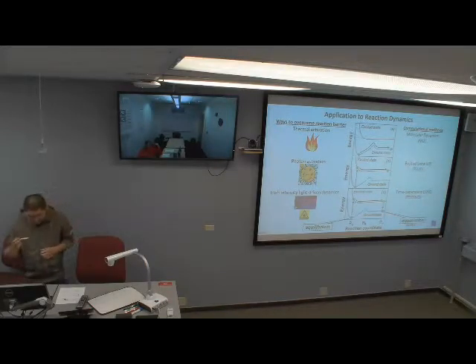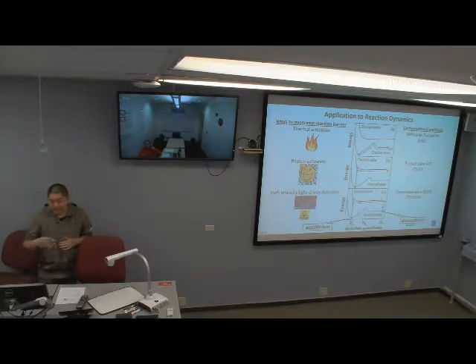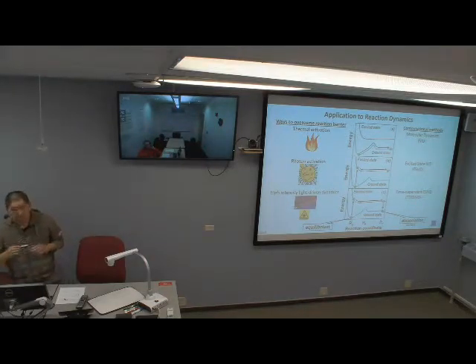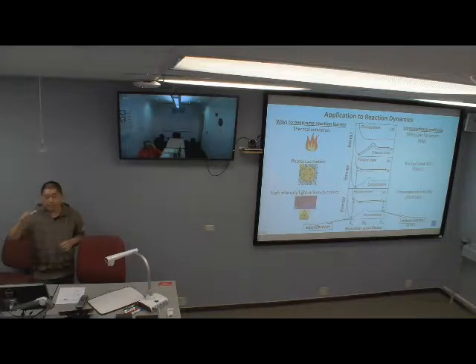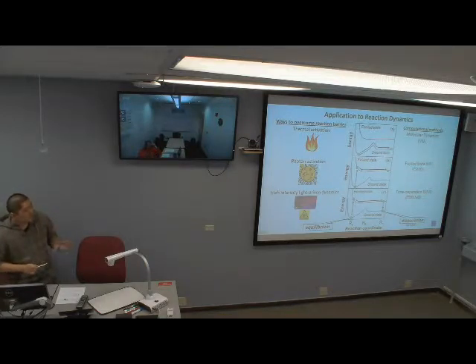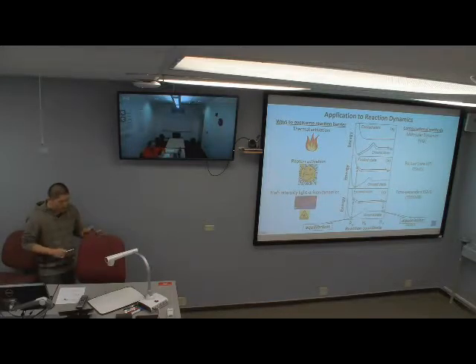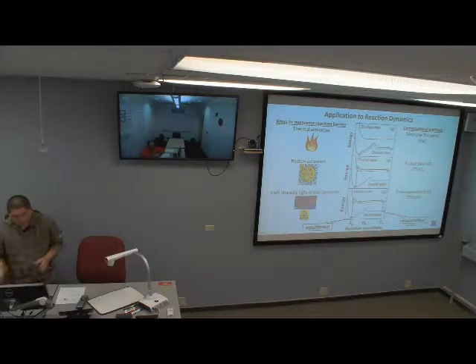And in TDSMD calculations, electrons are hopping between ground state and excited state. So first, the electrons are promoted from ground state to excited state, and then electrons are relaxing from excited state back to ground state. So this is called a Rabi cycle. TDSMD calculations consist of many Rabi cycles. During these Rabi cycles, the system accumulates kinetic energy and finally overcomes the dissociation barrier, leading to photodissociation.